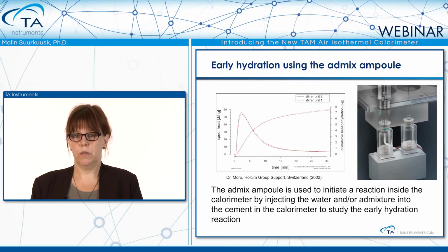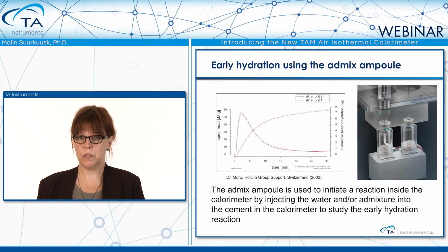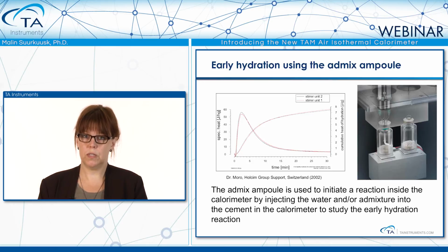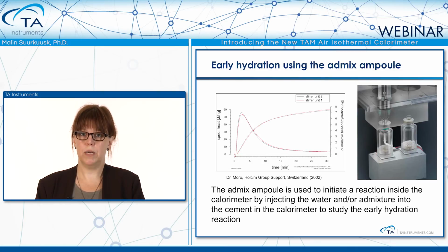For early hydration, if you're going to mix your cement sample outside for measuring 7 days of hydration, you can mix it in the ampule and put it into the calorimeter, but then you miss the first 10, 20 or 30 minutes of the hydration process, depending on how high the signal is. If you're interested in this first signal, then you should use the admix ampule. In the admix ampule, you will put your cement powder into the ampule, and then you will add water and mix it inside the calorimeter. And then you initiate the hydration reaction inside the calorimeter to be able to measure from the first injection of water. In the example here, you see 2 samples, and you can see on the time scale now, no, we're not on days, it's the first 30 minutes you're looking at here.